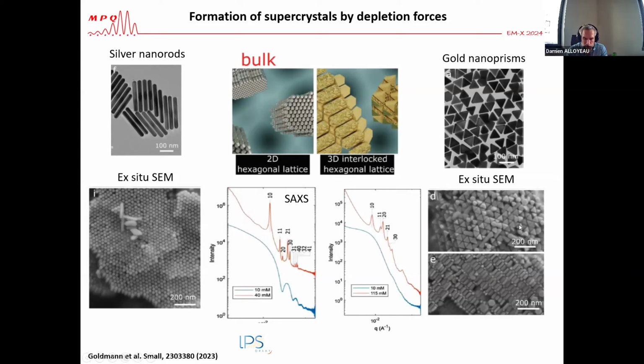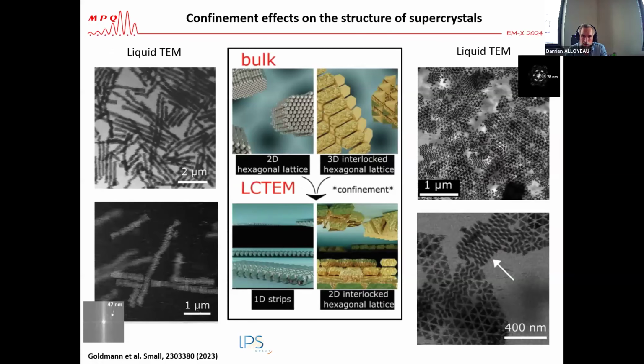by SEM observation. Now what's going on when you run the same experiment inside the liquid cell? We see that we form also supercrystals, except that the affinity of the nanoparticles for the membrane prevents them from stacking in the direction perpendicular to the membrane. So we end up with 1D strips of silver nanorods instead of the 2D hexagonal lattice, and a 2D interlocked hexagonal lattice for the gold nanoprisms. In fact, you can observe the interlocked lattice along different directions, but the ability to stack perpendicularly to the membrane is limited to 1 or 2 layers.